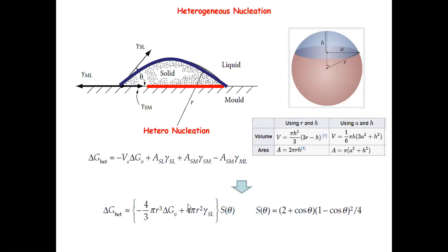It's the free energy difference for the homogeneous nucleation, right? So this is the bulk free energy reduction of a nucleus of radius r, and this is the associated interface energy contribution. And we'll only have one interface area consideration here, which is the solid-liquid interface. We do this through simplifications because the solid-liquid interface energy is the only intrinsic quantity here, right? Because I can put my water into a glass cup, a plastic cup, or a metal cup, and it doesn't really matter. But the liquid and solid interface is the intrinsic quantity here, so we keep that.